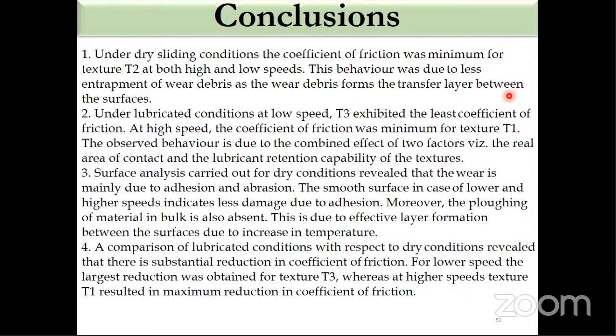And as I told you, plowing of the material in bulk was absent, which is because of effective layer formation and entrapment of the wear debris in the depressions of these textures. So you could see that reduction of coefficient of friction was observed for texture T3 for lower speeds, while for T1 at higher speeds, it was giving us maximum reduction in coefficient of friction. So these were some of the conclusions which we could draw from this study.